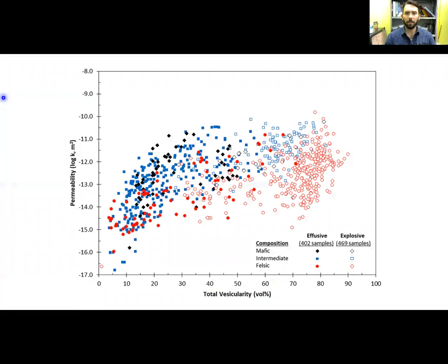So to set up the problem, I've made a compilation of published permeability-porosity data from natural, effusively, and explosively erupted products from nearly 40 volcanoes. Notice we have three distinct clusters of data. Low porosities are characterized exclusively by effusive data, while there's a heavy concentration of explosive products at high porosity permeabilities, with a transition zone in between where the data overlap.